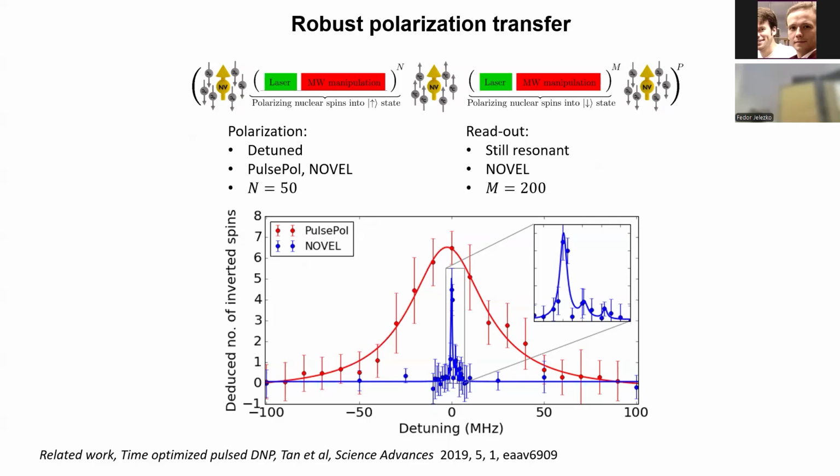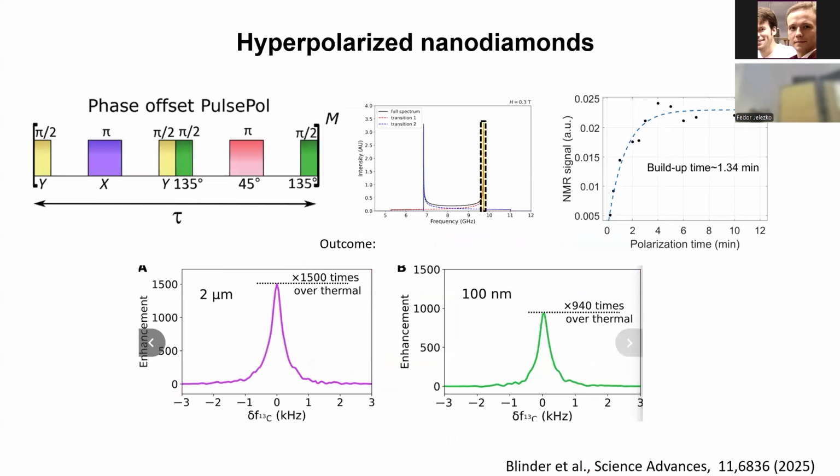And so this is a joint effort with Martin Plenio's team at Ulm, who did the design of this pulsed polarization sequences. Now this can be applied to these powders with all these elements. We have a pulse pol sequence for polarization transfer. We can apply it to powder spectrum, catching about 10% of the population of NV centers in this part of the spectrum. Actually, we also rotated the sample and the magnet to shuttle different nanodiamonds around, and with this we